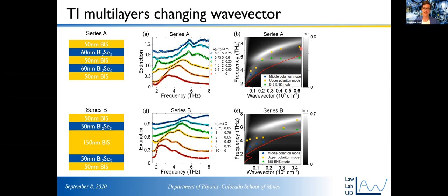And the upshot of this is that these solid squares or solid symbols, these are the extracted resonant positions. The color plot is his model. But this red line here is what we would expect if they were not coupled. So the point is that this is the dispersion we would expect if they were uncoupled, and that's not what we see at all. What we see is exactly what we would expect for coupling of these modes. And we can zoom in on this section here that I highlighted in light blue.